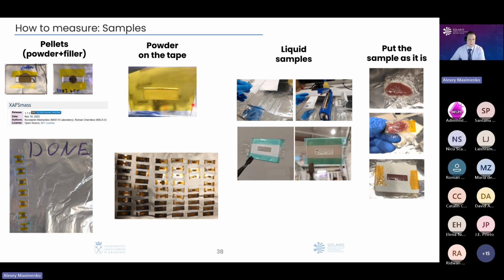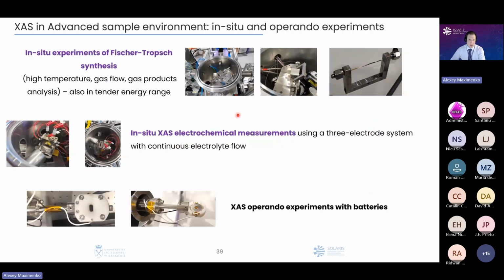Okay, so for example, thin films also could be measured without any problems, and it will be an analog of this powder on the tape, which we have here. So it means that almost all types of samples could be measured during X-ray absorption spectroscopy measurements. Also, what is important, we could provide in-situ experiments.